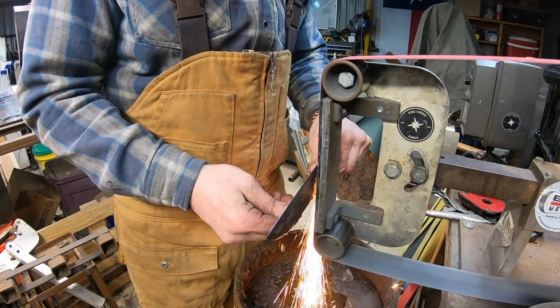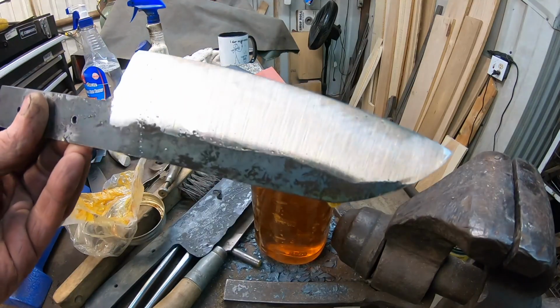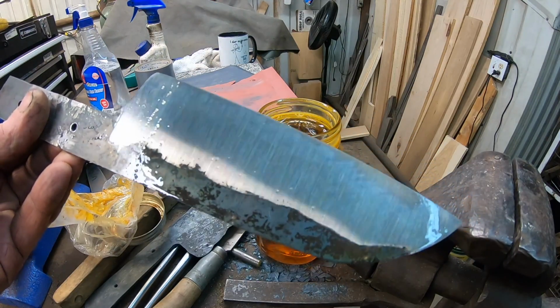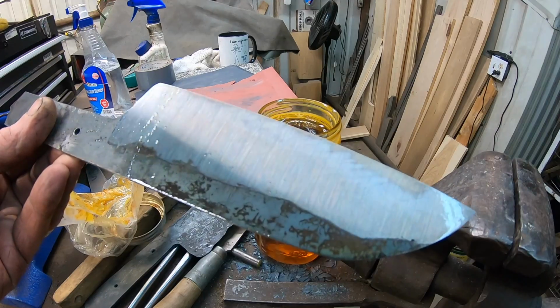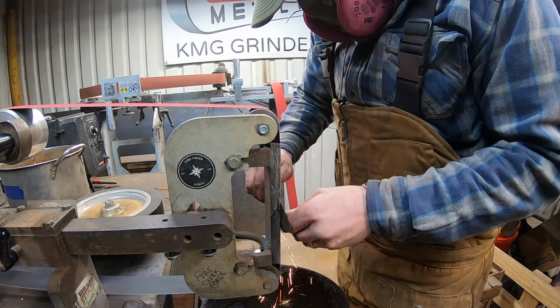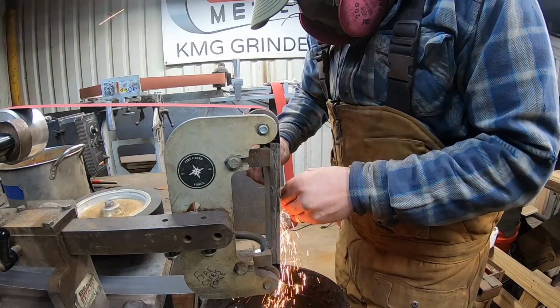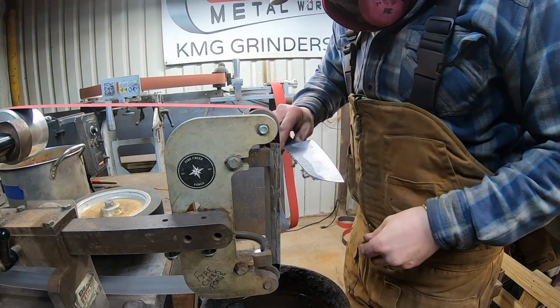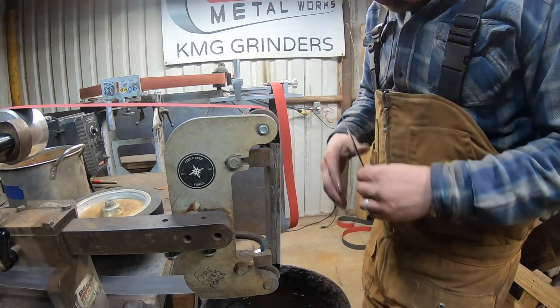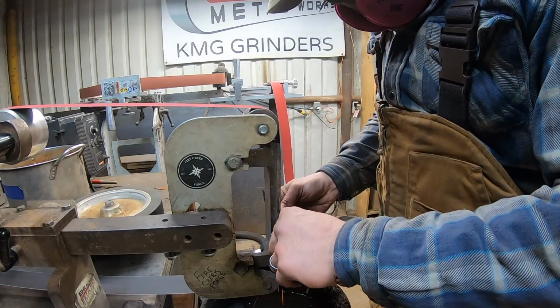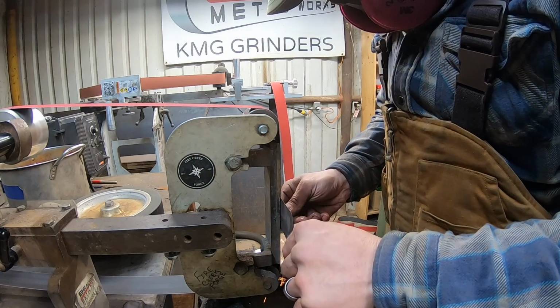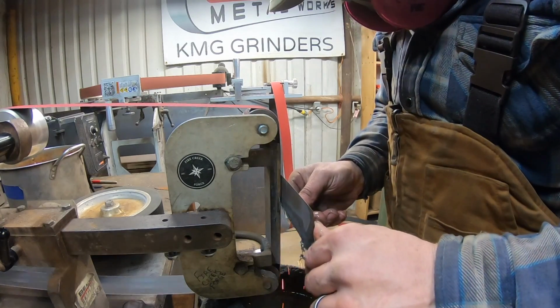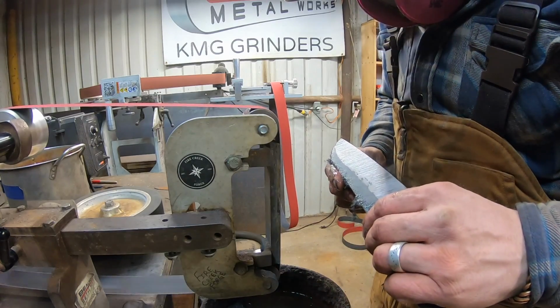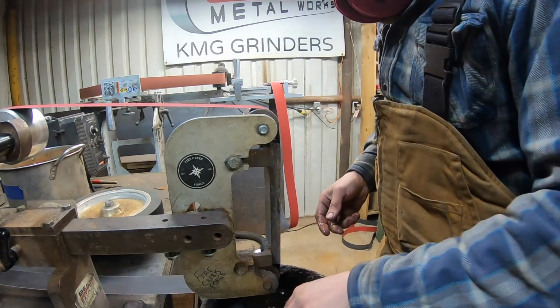Now, I ran my test block several times before testing my steel and after, and it reads consistently. And so rather than get up in the top and mess with the fiddly screws to adjust the calibration, I simply compensate on paper the 1.5 points. All that to say, we ended up with a Rockwell hardness of 63.5 to 64 on the finished steel.